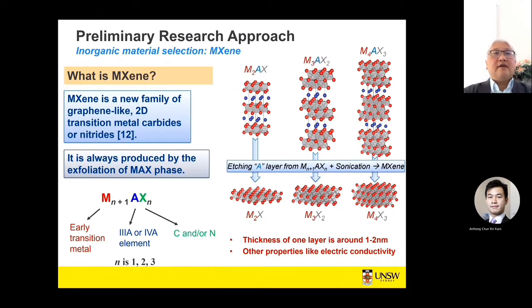So the material that we have discovered lately that could actually produce a lightweight fire resistant is MXene. So what is MXene? That's the question being asked. MXene is a new family of graphene-like 2D transition metal carbides. It is always produced by the exfoliation of the MAX phase. The beauty of this material is that it has a thickness of around 1 to 2 nanometers, and it's a 2D sheet of a couple of nanometers in size.